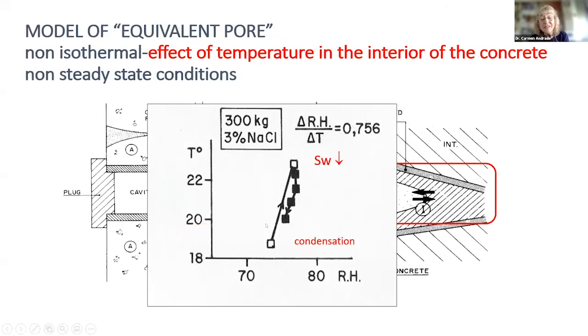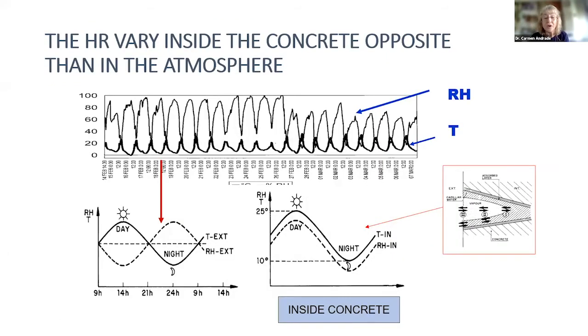Well, one thing that is interesting is that inside the pore, if I increase the temperature and I am not at the surface, the relative humidity increases because the liquid water evaporates. And in the morning the temperature increases until mid-time, and during the afternoon the temperature decreases. In that case, I condense. During the temperature increase, there is a decrease of the saturation degree, and during the lowering of the temperature, there is a condensation. And this is a complete cycle, that is a daily cycle and also a seasonal cycle.